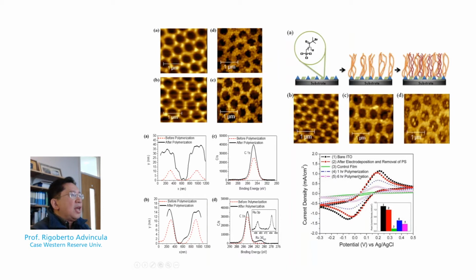On the other hand, since we are able to modify the hole with an initiator for ATRP, we can do a dual or binary composition in which the arrays are modified with a polymer brush, but then we can also modify the holes with another polymer brush having a binary composition. And in fact, we were able to characterize this based on the diffusion properties of, let's say, a molecular ion probe using cyclic voltammetry as a method to look at the diffusion of polymers on a conducting substrate.